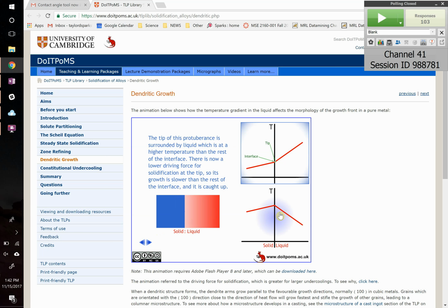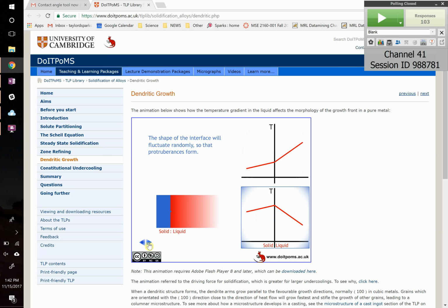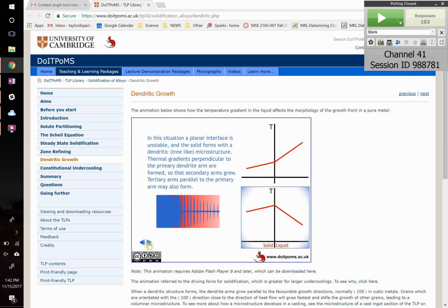You can have another scenario. If your mold is at such a high temperature that it's really close to the temperature of your liquid, and your material absorbs energy as it solidifies, which is not uncommon, it changes this scenario. Now, let's say that some sort of perturbation forms, some little bit from the liquid phase forms a little bit of solid right here first. In doing so, that lowers the temperature even more of the liquid nearby it. So that's going to cause this thing to grow out into the liquid. They call this branch instability, where basically there's a driving force for it to keep on growing out, because the tip where it's growing is at a lower temperature, so it's going to keep on solidifying at the tip first. And so it grows these weird Christmas tree looking things. That is the dendritic structure. You'll see this all the time in metal alloys. It's very, very common, and you'll wonder where on earth it's coming from. It has to do with the temperature upon cooling this alloy down.